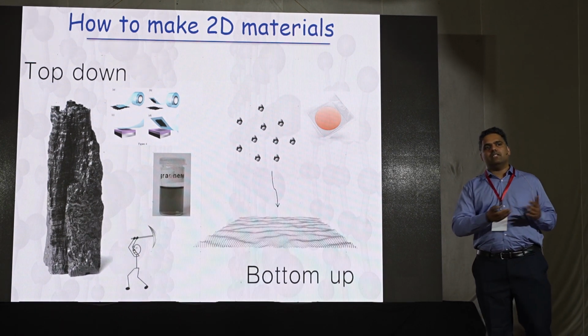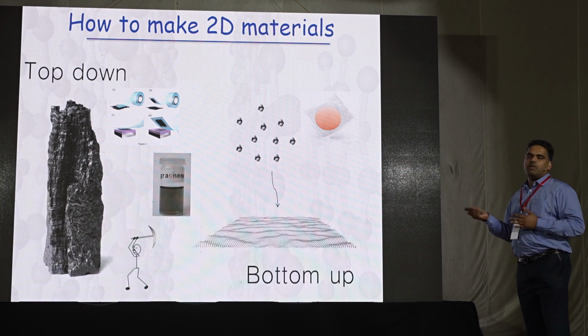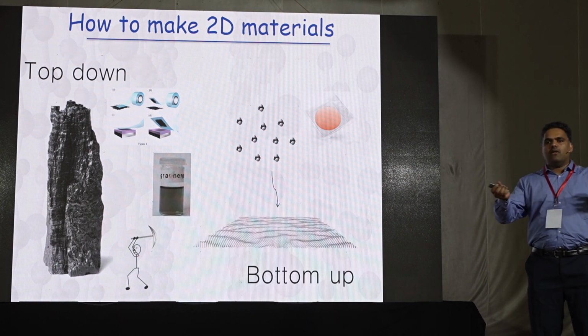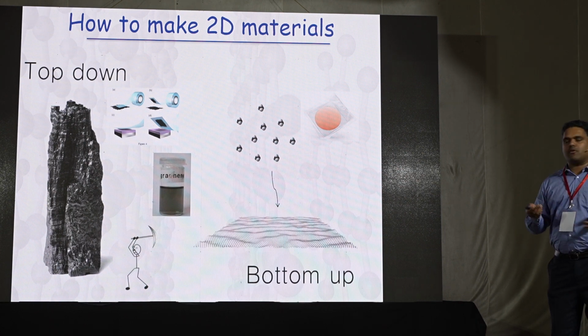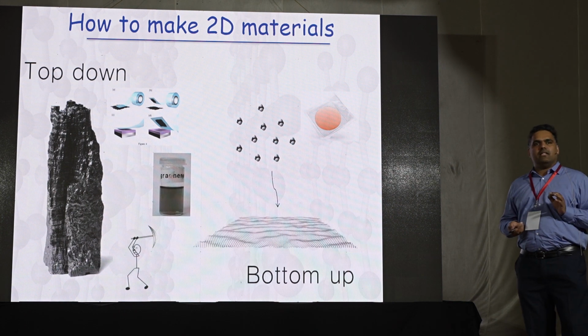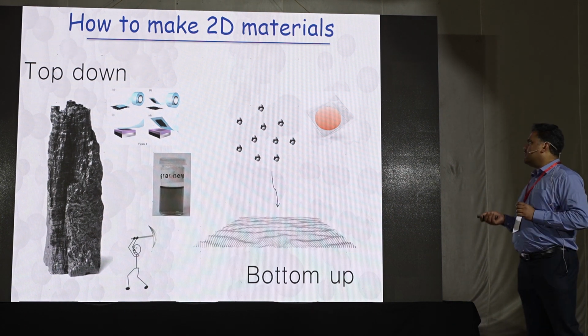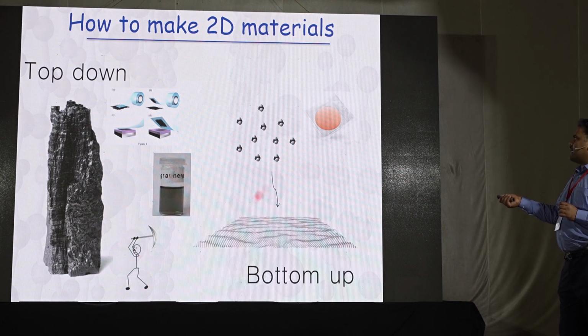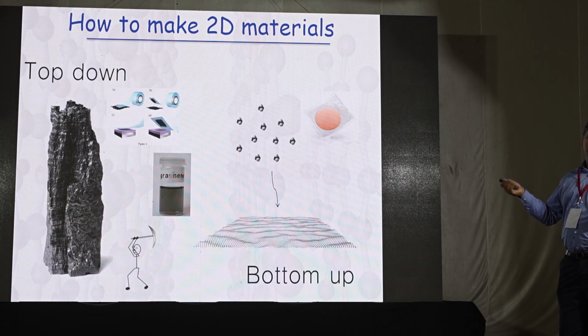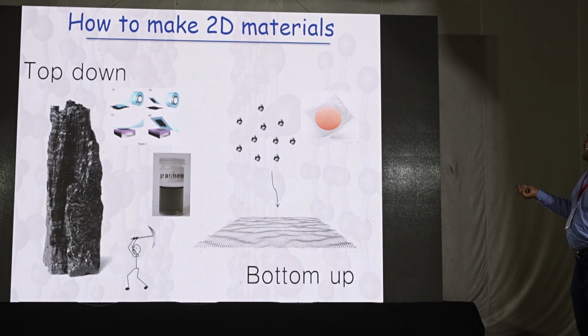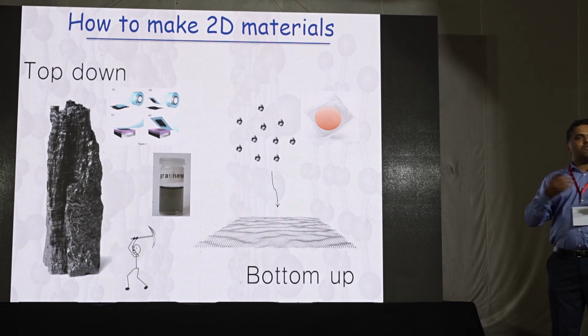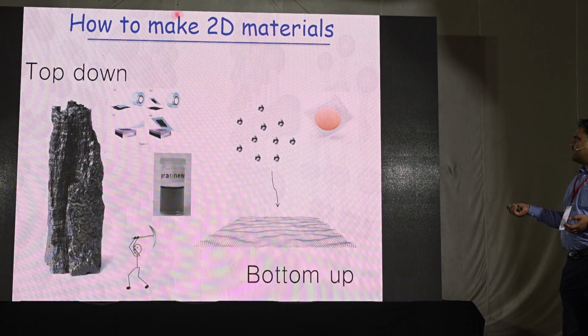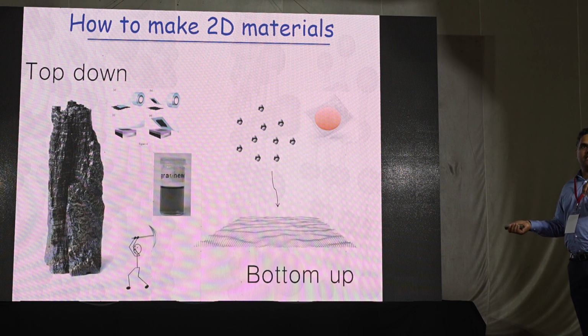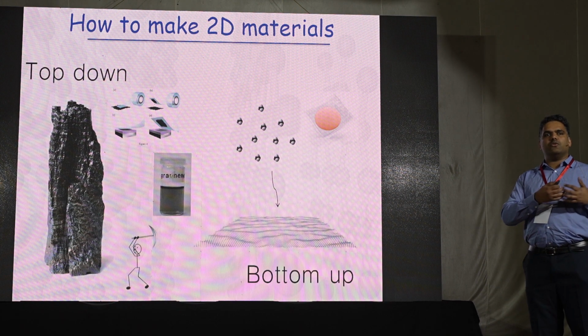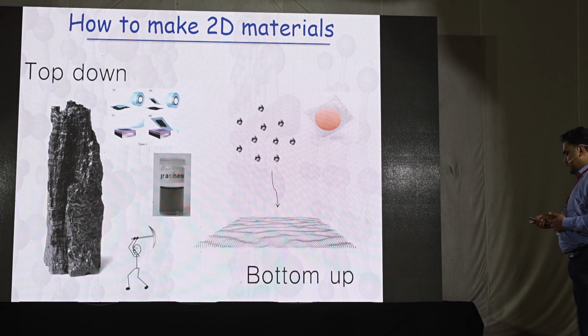The second approach, this is the original approach what people used, that is a top-down approach. What you do is you take a crystal, break it down into single layers of atoms. Again, there are different approaches there. The method which provides the best quality graphene or 2D material is still the mechanical exfoliation. We call it micromechanical exfoliation. It's a fancy name, but it's nothing but peeling with a tape. Then we can use different chemical methodology, intercalation, exfoliation, and so on. Then you can create graphene in solution form. It's called dispersion, graphene dispersion. It's nothing but you take a piece of graphite, put it in certain solvent. It could be water, it could be organic solvent, and so on. Then you sonicate it for some time. You get dispersions of different 2D material.